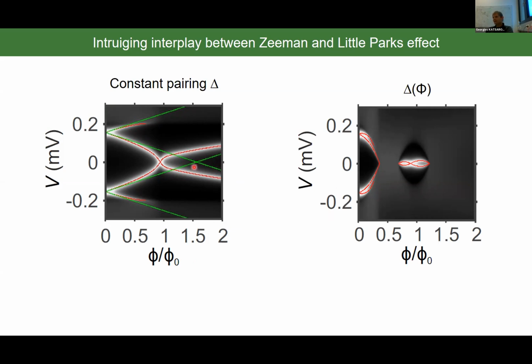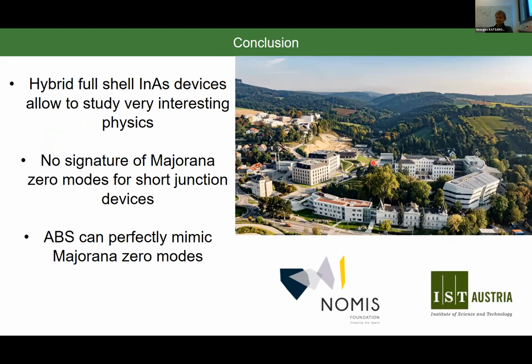So you can see that the position where the zero bias peak has emerged has completely changed. And due to the modulation of the gap with the flux, practically you cannot distinguish the splitting of Andreev bound states. So you would see one blurred subgap feature or barely a feature appearing at delta, and then you would get a zero bias peak in the first lobe. But more about it, you will hear in Fernando's talk, who is going to give you much more insight into the theory behind it. And with that, I'm already at the end of my talk.